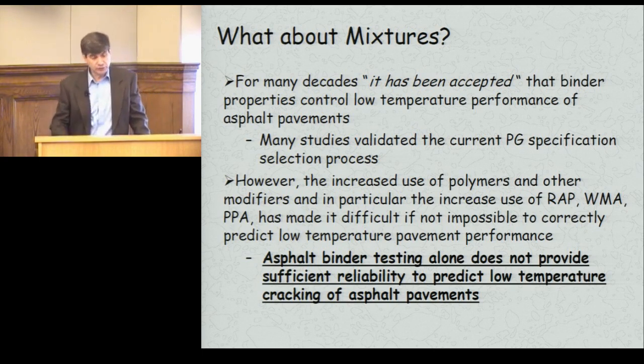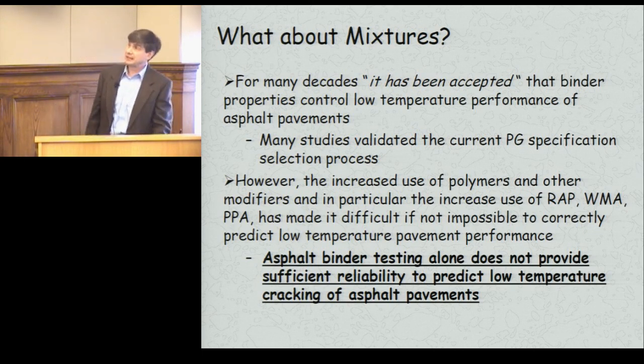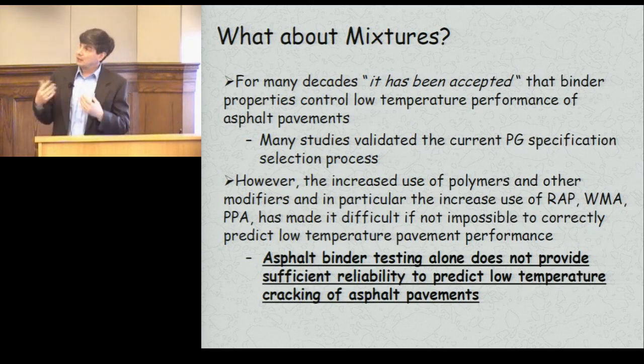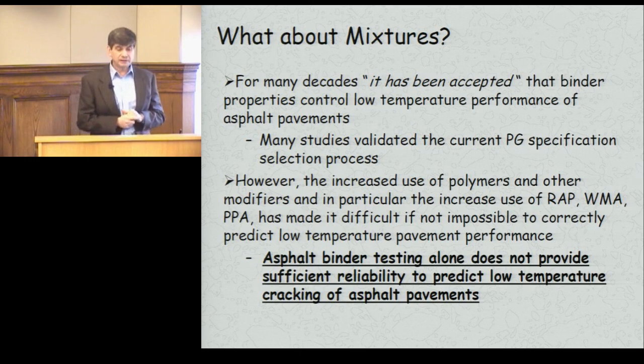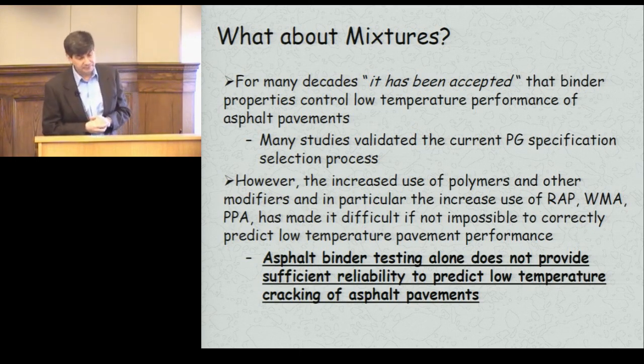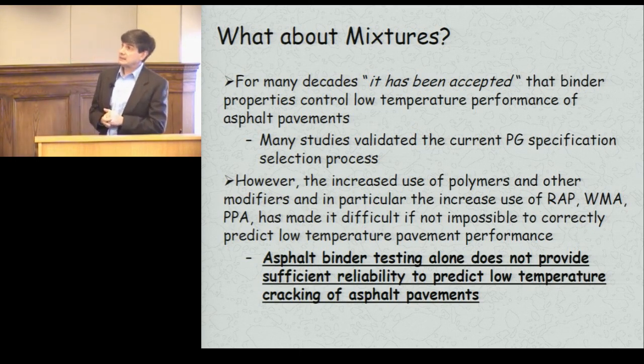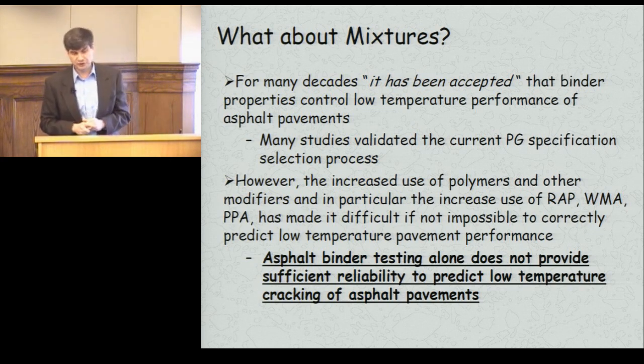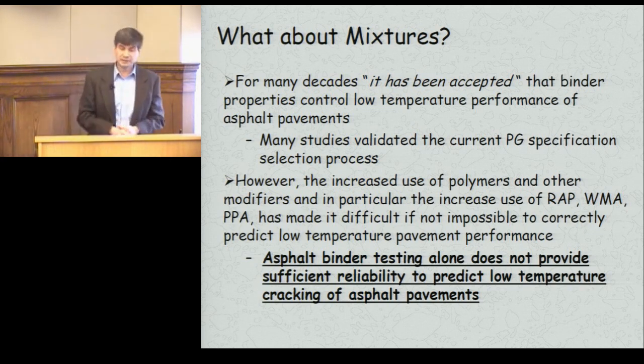We started to use more asphalt modifiers, and in particular when we started to use recycled asphalt pavement, the new technology warm mix asphalt, and this other additive called polyphosphoric acid, or PPA. All of a sudden it became difficult to use binder data to predict what mixtures were, because the mixtures were different. I mean, not all of a sudden, but now you started putting other things into the asphalt mixture.